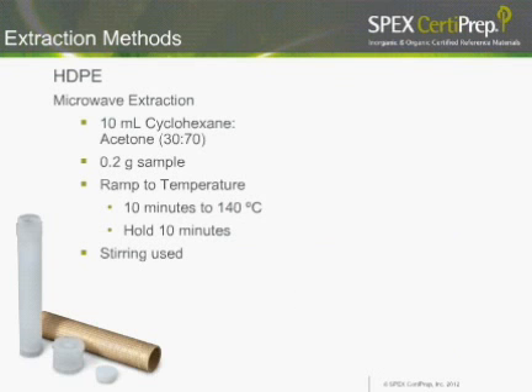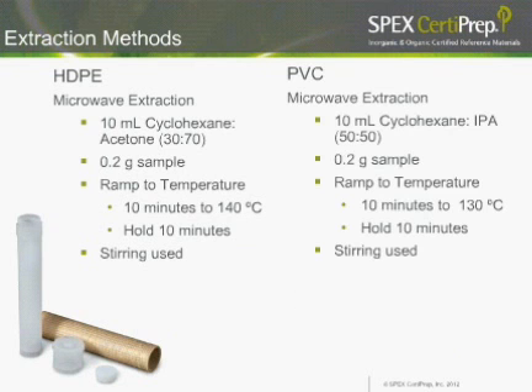The method we used for the HDPE was the same method prescribed: 10 mL of the cyclohexane-acetone at a 30-70 mix. We decided to use less sample, 0.2 grams, and we ramped over 10 minutes to 140 degrees C, where we held for 10 minutes, and we did use stirring for these samples. For the PVC, we have our optimized method, which was 10 mL of the solvent, cyclohexane and IPA at 50-50, 0.2 grams of sample, ramping over 10 minutes to 130 degrees C, and we held it for 10 minutes. Again, stirring was used.